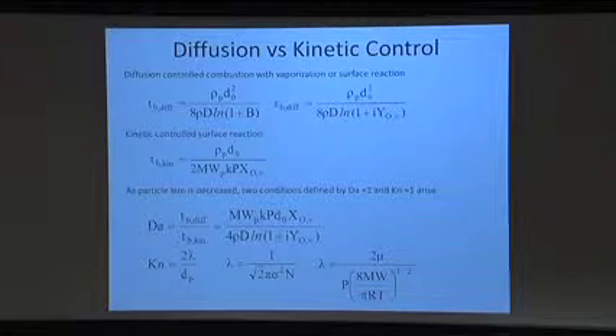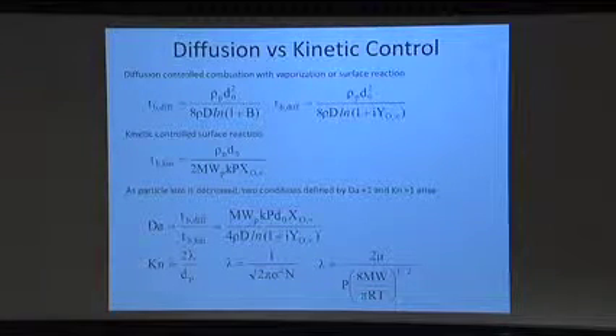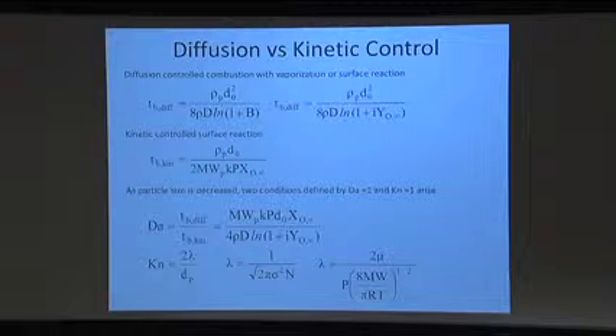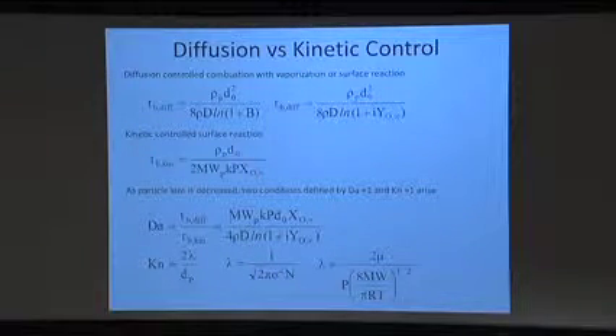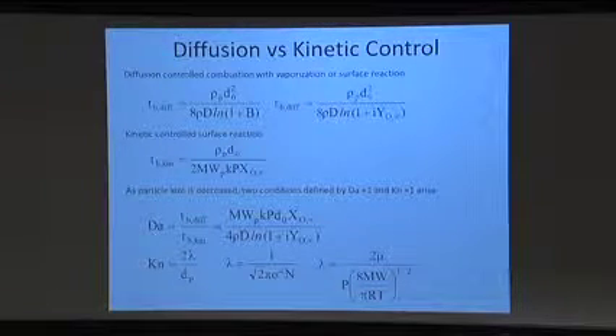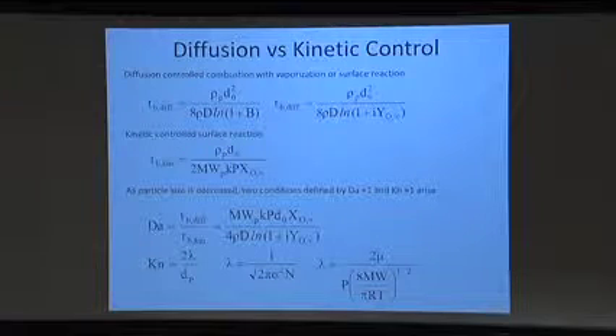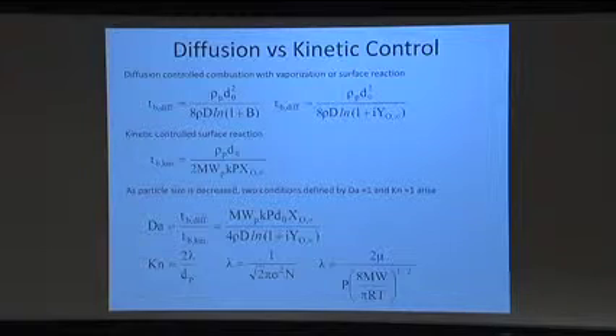I can change this situation, so suppose now I have the surface as being where the reaction occurs, but it's still mass transport controlled in the surrounding. I again find that the time here for the burnout is proportional to the original size of the diameter of the particle squared. Okay, and the driving force is still now related to how much oxidizer is in the surrounding environment.